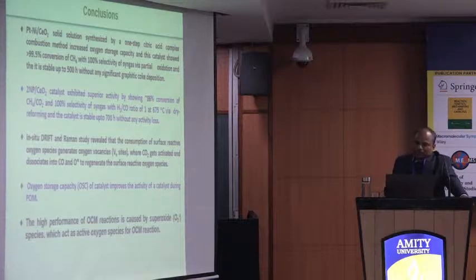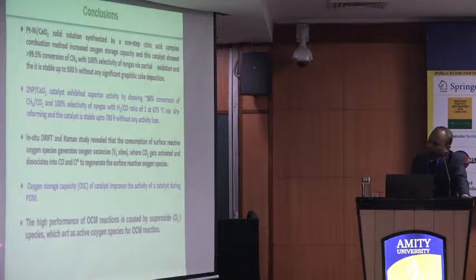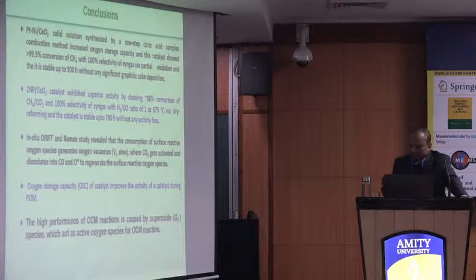And in situ DRIFTS and Raman study revealed that the consumption of surface reactive oxygen species generates oxygen vacancy, where CO2 gets activated and dissociated into CO and O*, to generate the surface reactive oxygen species. And for the oxidative coupling of methane, we found that the oxygen storage capacity of the catalyst improved the activity of the catalyst for this reaction. The high performance of the oxidative coupling of methane reaction is caused mainly by the presence of superoxide species, which is the active species for this reaction.